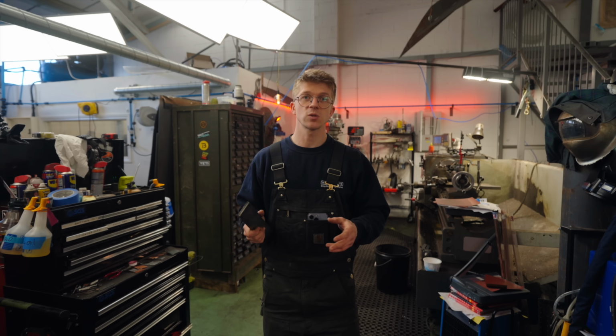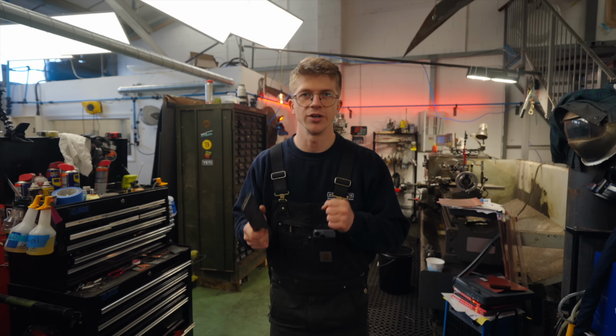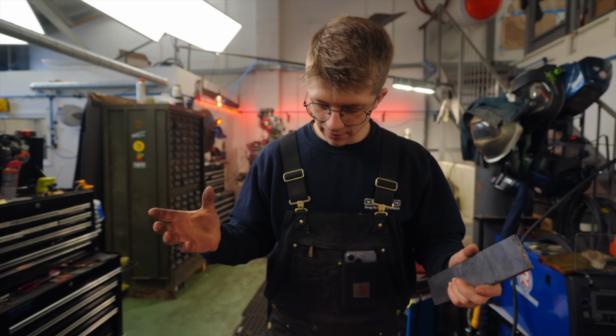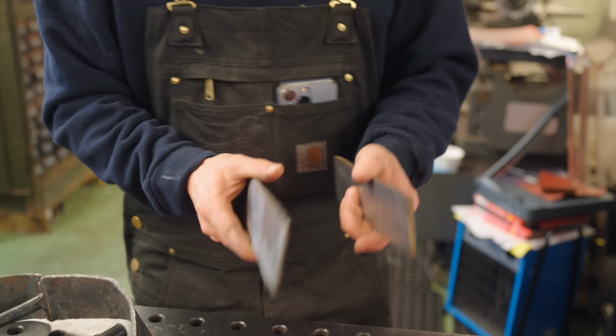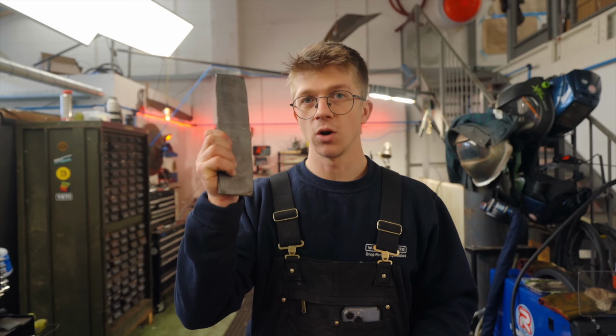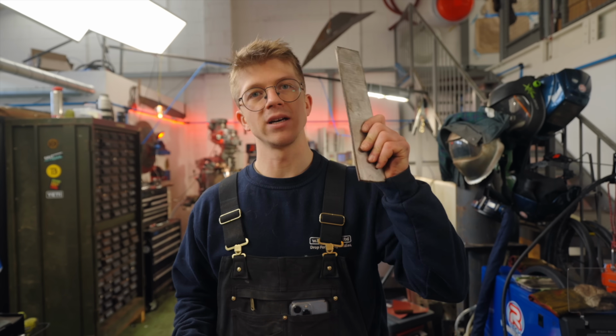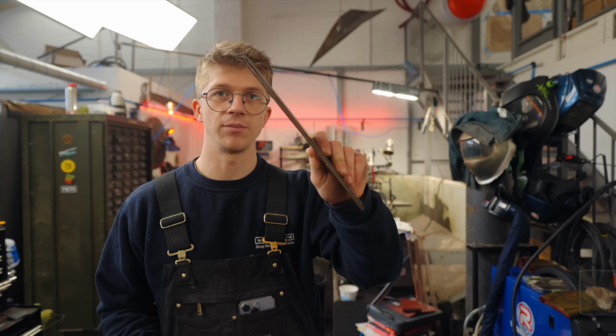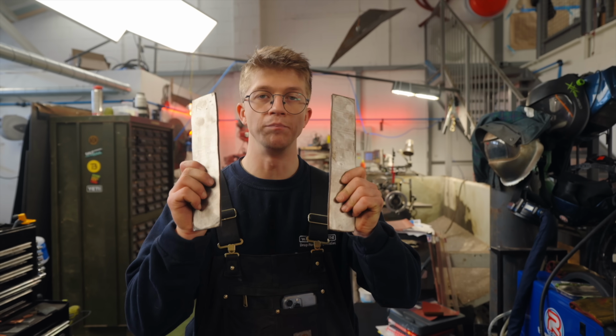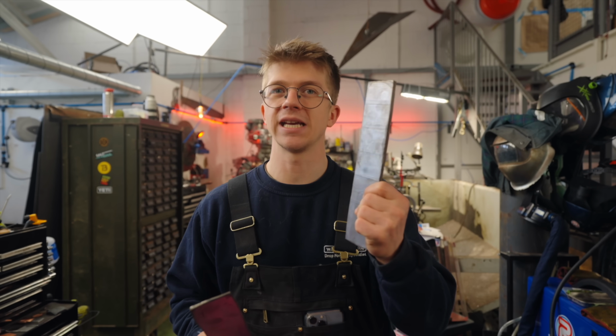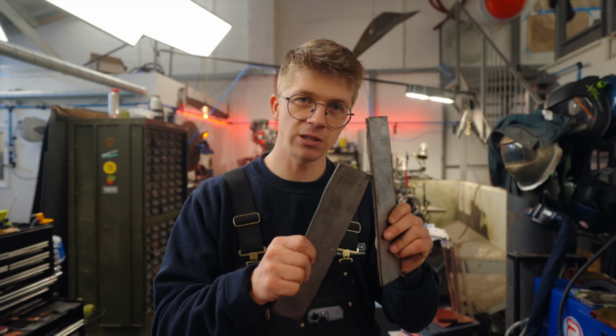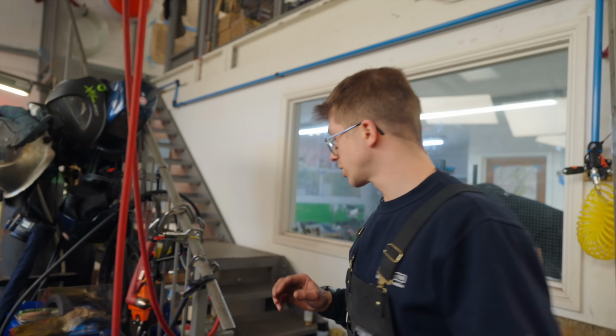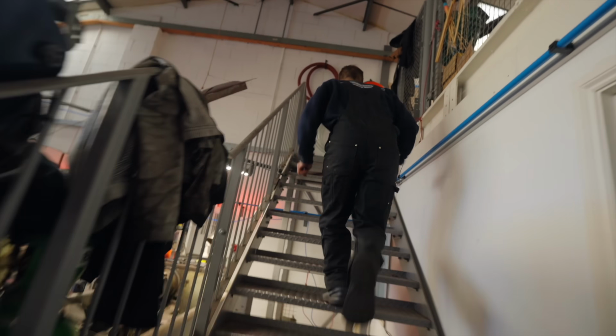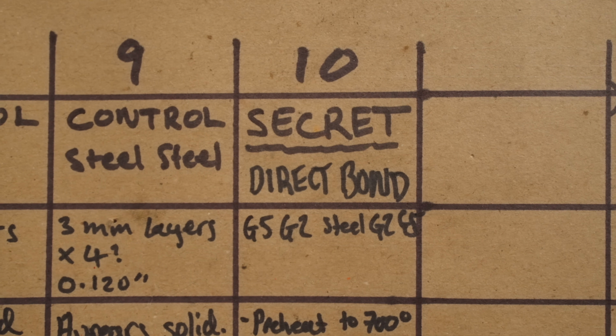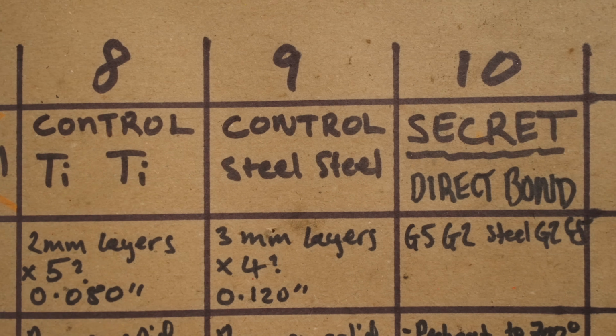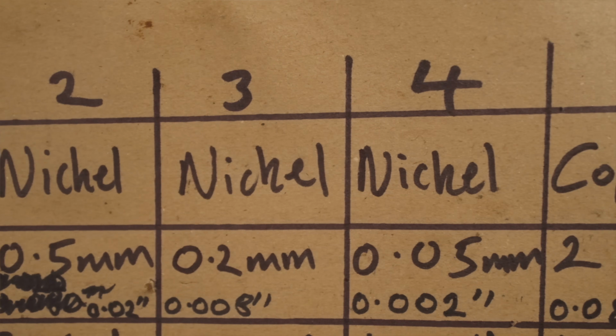You remember these sets of experiments were meant to be about how the steel gets hard. Will it get hard enough? Well, I don't have great things to measure here other than our half-failed oil quench sample and our hopefully successful water quench sample. I want to test the Rockwell hardness of both of these to see if water quenching is at least our way to achieving a steel core of the appropriate hardness. We're also going to run up and grab some of the samples from last time. We're going to grab that direct bond sample, number 10, our control steel sample, one of our nickel interlayer samples as well.